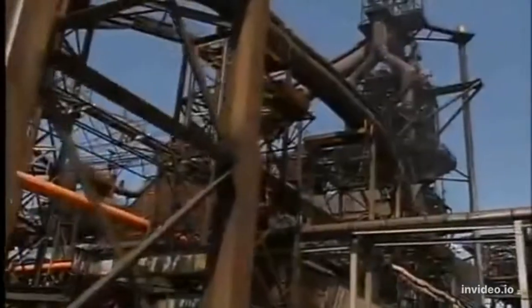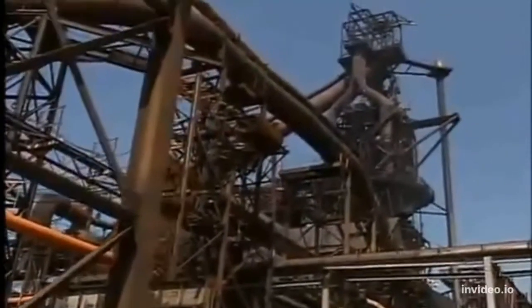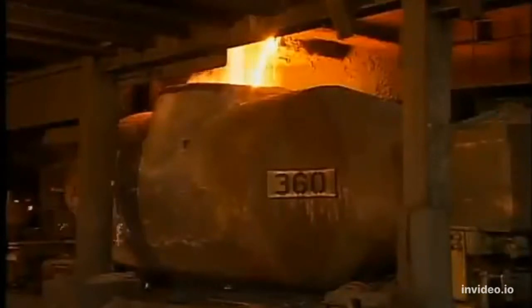The fuel and pellets come together in the blast furnace, where we add just enough limestone to remove impurities. From below, a continuous blast of superheated air combusts the coal, intensifying the heat and changing raw materials into molten iron. Sometimes more than 9,000 tons of it a day in our largest blast furnace, where it reaches a temperature of 2,700 degrees Fahrenheit. At regular intervals, we tap this blistering brew into giant submarine ladles that ride on rails to the basic oxygen chamber, where iron will be turned into steel.